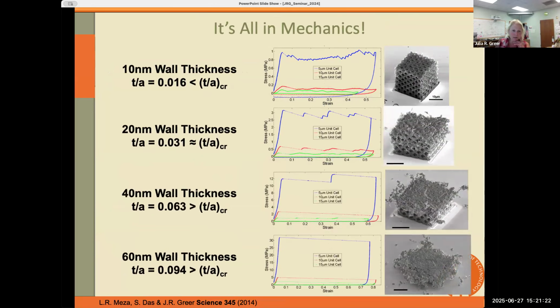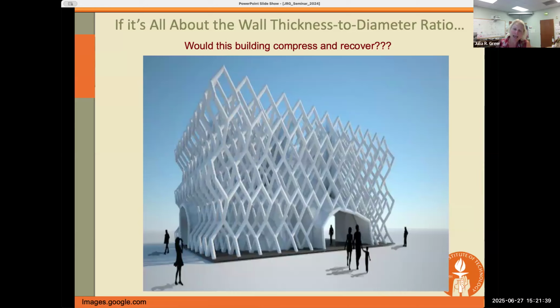And as we increase the wall thickness in the first approach and supersede the critical T/A ratio, you can see that the deformation becomes a lot more stochastic, a lot more catastrophic, and these nanolattices are no longer recovering at all. So it turns out that the answer lies in mechanics. Well, if that were true, that means that if we were to construct a building where each wall is represented by maybe 10 centimeter thick tubes, and the radius is 3 meters wide, and the whole building maybe spanning multiple kilometers, we should observe the same response, right?